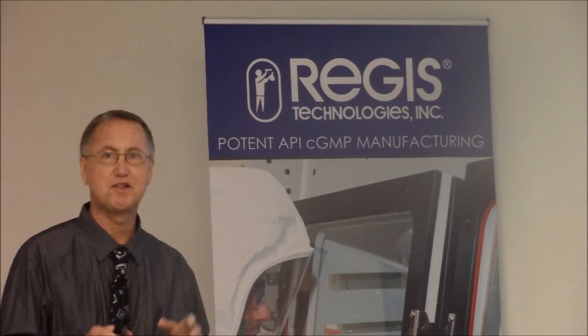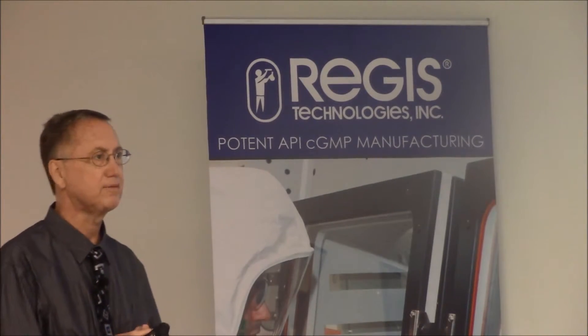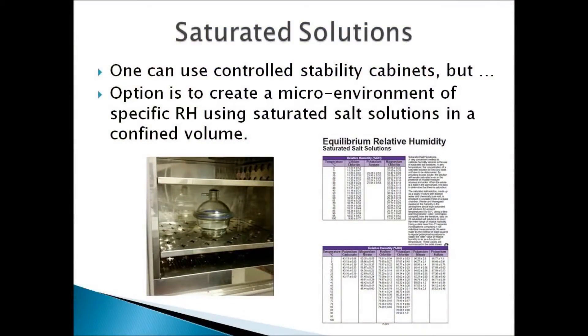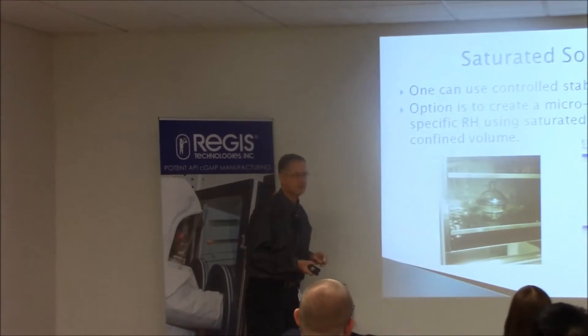For creating a micro-environment for forced degradation, I like 55°C and 80% relative humidity — it seems to hit things just right and is easy to attain. We use a typical oven set at 55°C, with a dry control sample sitting out in a vial. For the humidity condition, you place the samples into a desiccator — which is not being used to keep things dry here, but simply as a convenient chamber. It's convenient because there's a reservoir at the bottom where you can put a saturated salt solution.